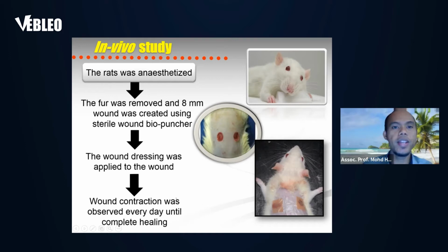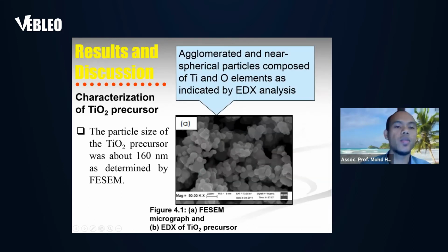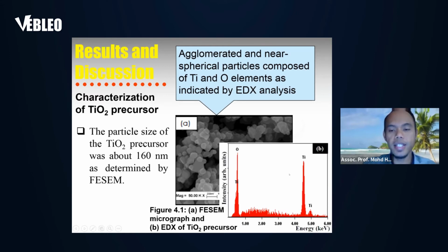And then we move to results and discussion. First, we characterize to confirm the formation of titanium dioxide nanotubes. Okay, this is the precursor. We use titanium dioxide powder. We measured and observed 160 nanometers for the commercial one. And then this is EDX analysis to confirm the presence of titanium and oxygen elements.